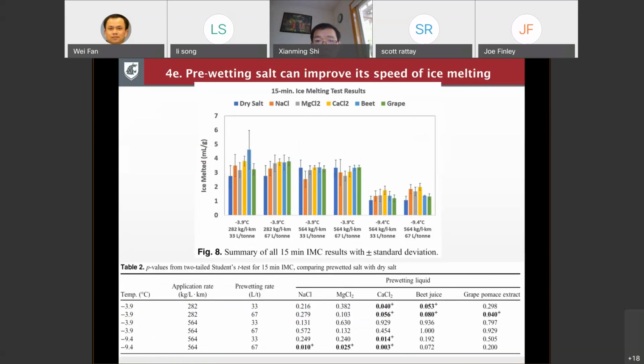Now, another thing is, what about the speed of ice melting? We look at 15 minutes. Sorry, I forgot to mention earlier numbers were all 60 minutes. So what about 15 minutes? Does the pre-wetting, like most practitioners would imagine, speed up the rate of ice melting? Yes, they do in most cases. Again, statistical numbers, if the number is smaller than 0.05, we think there's significant difference, statistically speaking. And yes, in many cases, it's statistically different.